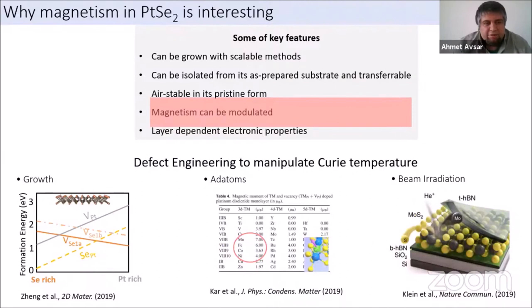And another cool thing about this magnetic ordering, this extrinsic magnetism in the platinum selenide, is that depending on the defect concentration, you can really manipulate the magnetism. So it gives you an opportunity to do atom-by-atom control of the magnetic ordering in these materials. Depending on whether you are growing your material under a selenium-rich or platinum-rich environment, you have a different type of defect concentration, okay?